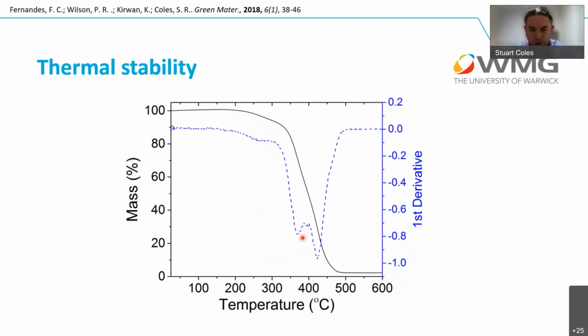And there's actually two profiles as part of the degradation as well, which again aligns with the fact that we've got two different backbones of the polymers in there, with our more aromatic DGEBA epoxy plus the vegetable oil epoxy material as well. So again, these results indicate that the polymer is in there. We are seeing a blend of these two materials.